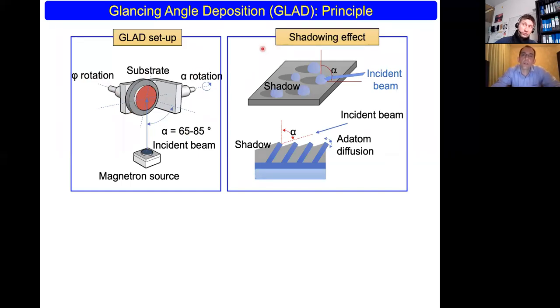Okay, now about the principle of nanorod growth. If you consider that atoms are already deposited on the substrate, these atoms create a shadow for the other incident atoms. And due to the limited atom diffusion, we can eventually produce slanted nanorods. However, if we rotate the substrate with respect to the deposition rate of the materials, the nanorods will grow vertically.